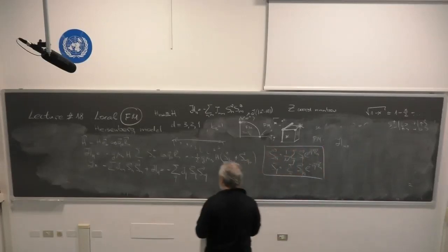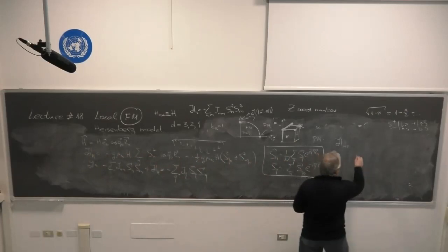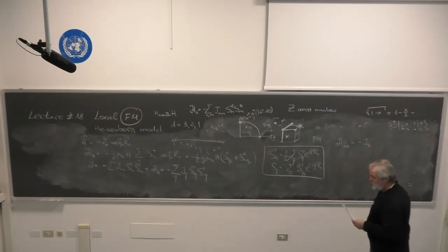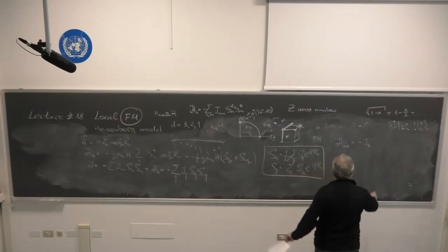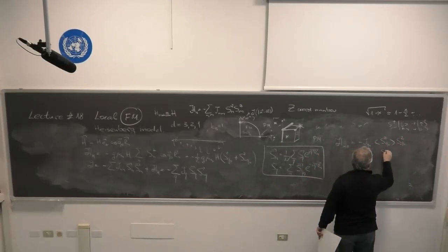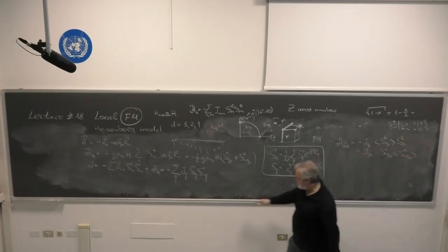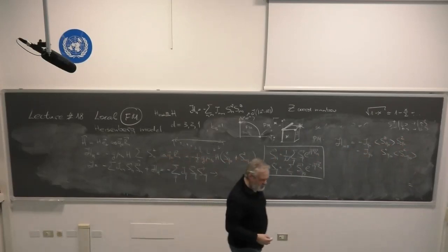So what I said is that in this Hamiltonian I will apply mean field, therefore I will replace one of the spins by its mean field value. So I will rewrite this Hamiltonian with J_Q node, because I'm interested in only one component, Q node, being activated. So I take S^z_Q node, S^z minus Q node, and so on. I first replace by averaging the first term, and then I replace by averaging the second term.